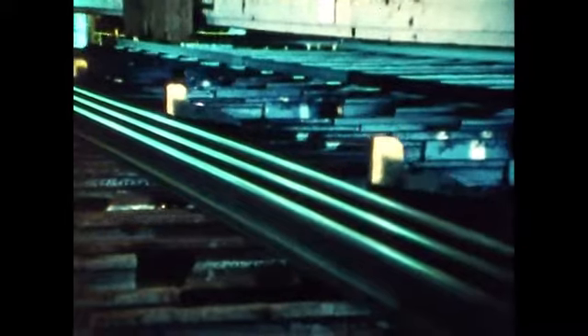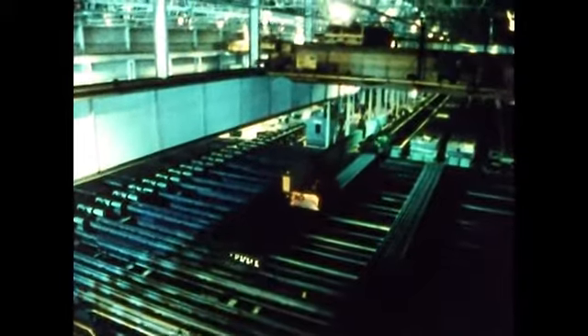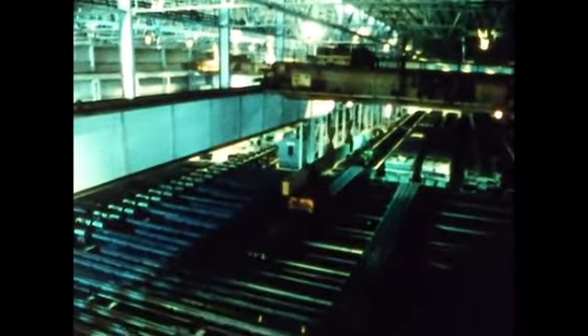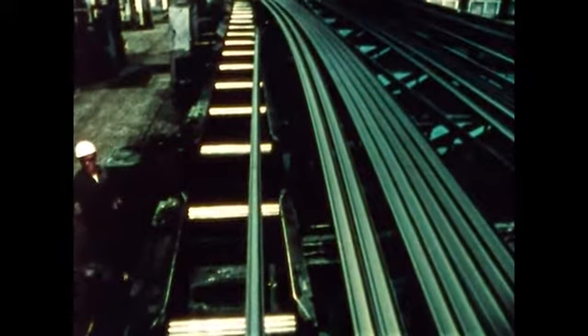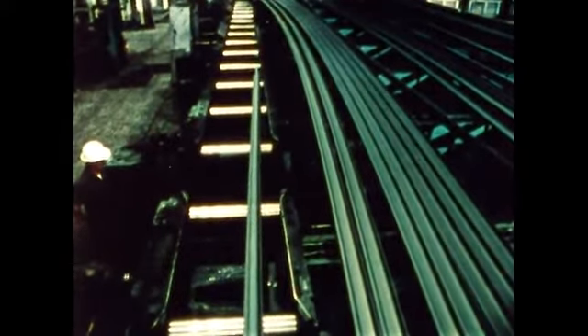On the cooling bed, the rail is finally turned onto its base. When it is cooled to a point where it can be picked up safely, between 725 and 1,000 degrees Fahrenheit, it's moved into the cooling boxes. The cooling boxes have been designed to meet American Railway Engineering Association specifications and will contain the rail for controlled cooling to 300 degrees Fahrenheit or less. This takes a minimum of 10 hours, but typically rails remain in the boxes for 15 to 20 hours. Controlled cooling has proved to be a successful method for eliminating hydrogen.